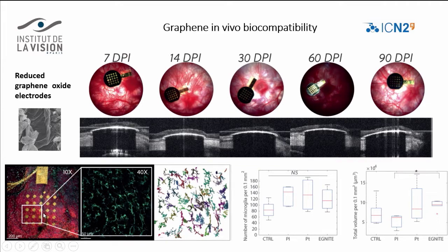And you see here above the electrode, we can count the microglial cells again. We can model them to really be sure that we count individual cells, and then compare this number of cells here. As a contrast to the control, here we have the polyimide, here the platinum electrode, and here the graphene electrodes. You can see that, in fact, there is no significant difference between all these conditions. Polyimide is classically considered to be biocompatible, and with our graphene electrode, we have a similar counting. So it means that the graphene is not introducing any incompatibility